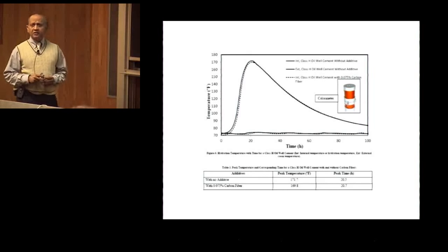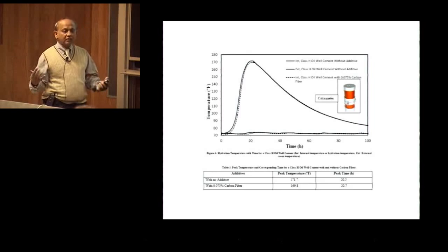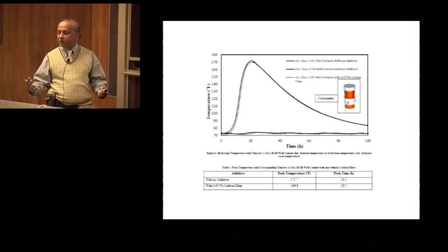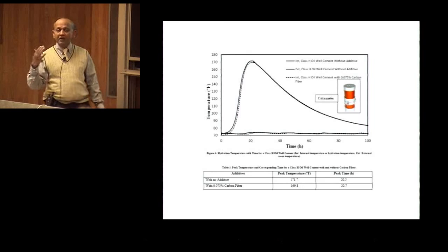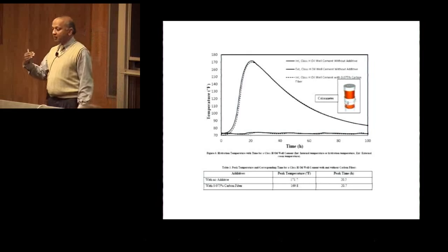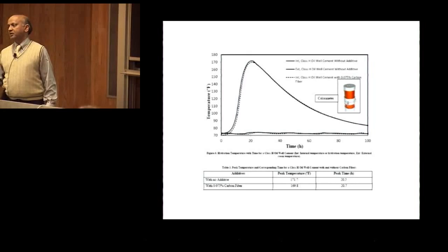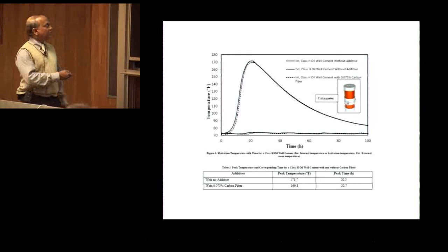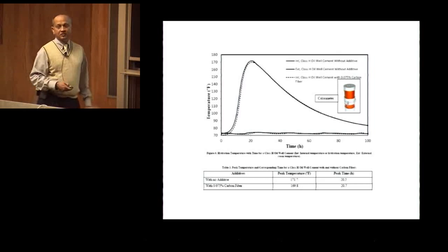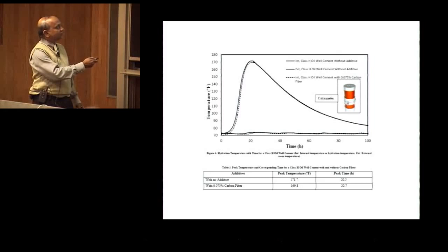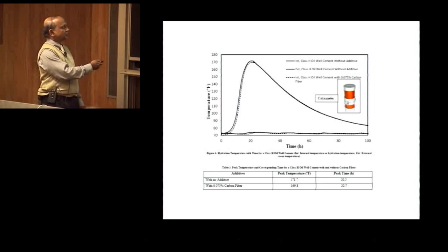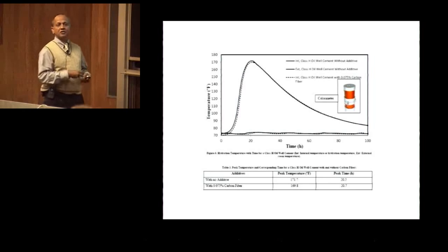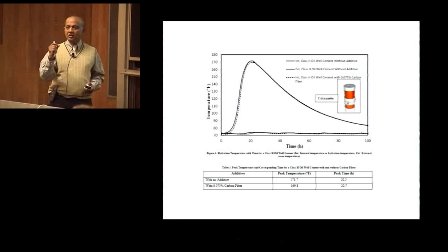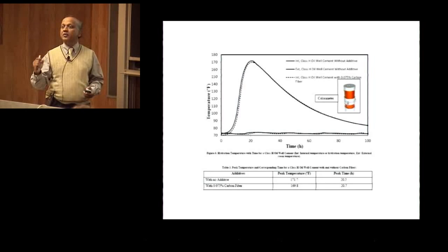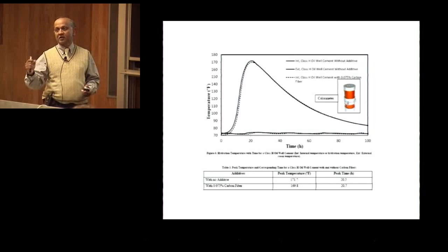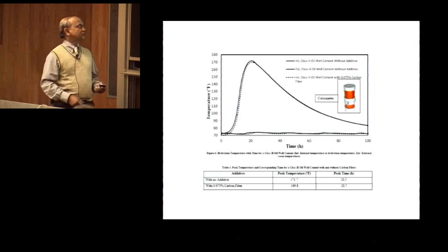Also, another thing that we do as researchers is that we want to take the cement and modify it, but we don't want to change the cement too much. So with our additives, this is where the interest is, our changes are less than 0.1% of the cement, very little, and we are proving that it will not even interfere with the hydration of the cement. This is a calorimetric study just to monitor the cement hydration with different additives. We put in different additives to look at it. We also work with nanotechnology and other technologies, just to show you the indicators, because we have to be very careful. We don't want to change the current practice. We want to enhance the current practice by making the cement smarter with a monitoring system. So you can see it.